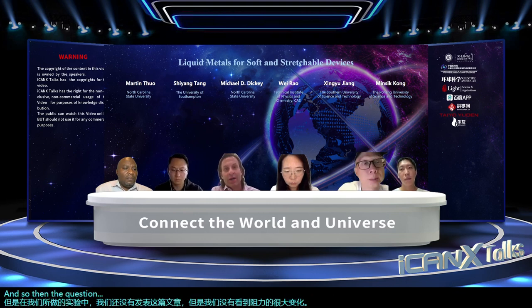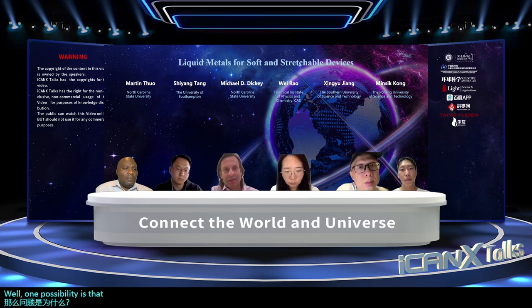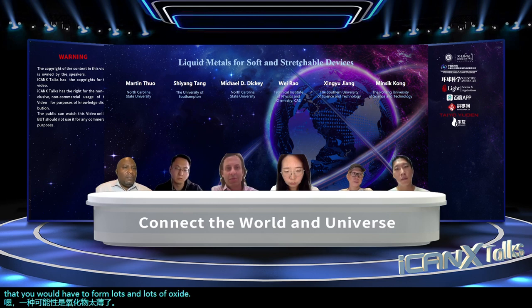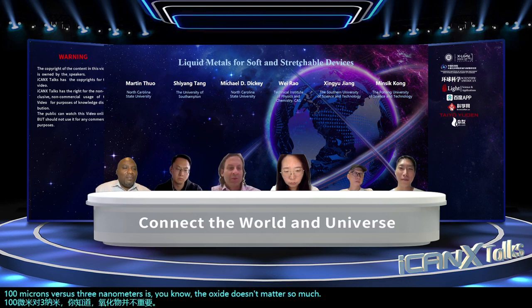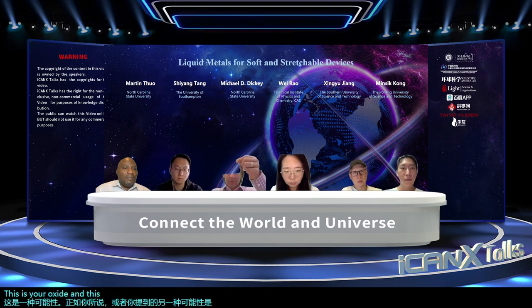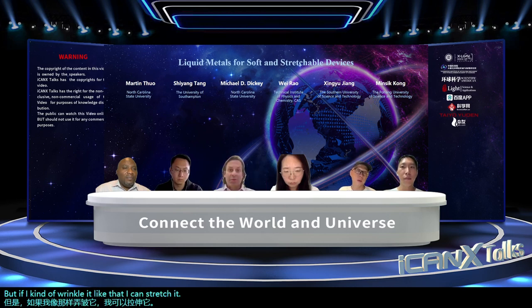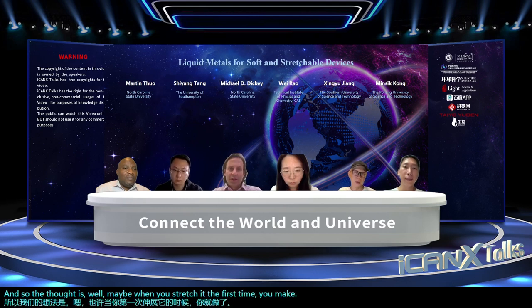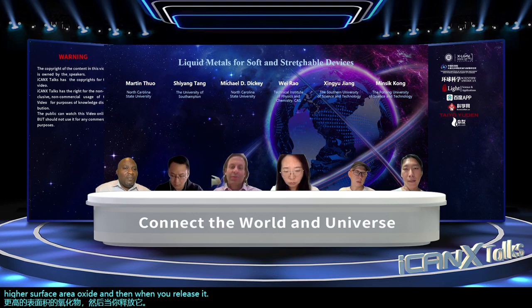And so then the question is why? Well, one possibility is that the oxide is just so thin that you'd have to form lots and lots of oxide before you really see a difference in a wire that's 100 microns in size, right? 100 microns versus 3 nanometers, the oxide doesn't matter so much. So that's one possibility. Another possibility, as you alluded to, is that if this is your oxide and this is a piece of paper, it's not stretchable. But if I wrinkle it like that, I can stretch it without actually breaking it. And so the thought is, maybe when you stretch it the first time, you make higher surface area oxide. And then when you release it, it would just wrinkle.